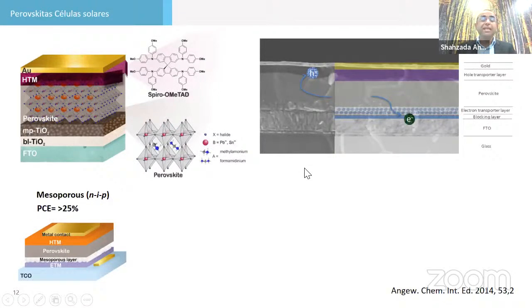As I said, the perovskite is a light harvester material with a thickness of almost 400 to 600 nanometers, sandwiched between two types of charge selective contact, N type and P type. Then we finish the device with a metallic contact, gold or silver or any metallic contact. The perovskite absorbs light and generates electron and hole pairs, and they then travel to their respective electrodes. To harvest the light effectively, we put an additional hole transport layer here, and on the bottom, an electron transport layer.